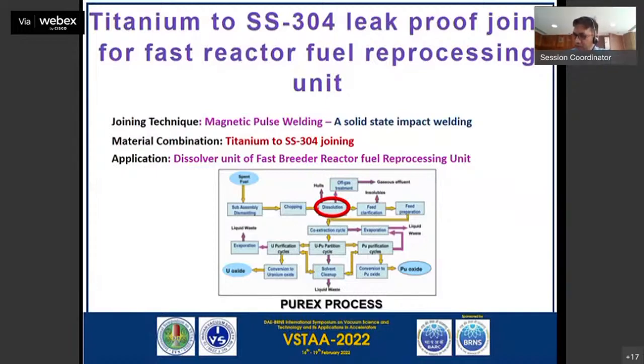I am working in the Pulse Power Electromagnetic Division, BARC Vishakhapatnam. Our division is into various applications of pulsed power. One such application is magnetic pulse welding, which is a solid state joining technique wherein there is no application of heat to join any metals. Usually in conventional welding techniques, we apply a heat source to melt the materials and let them solidify to get joined. But in magnetic pulse welding, there is no such heat. It is a solid state impact welding.